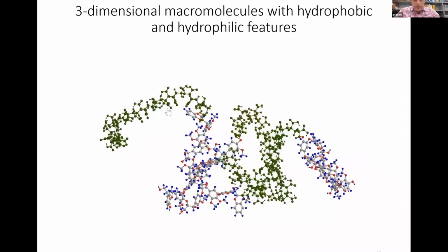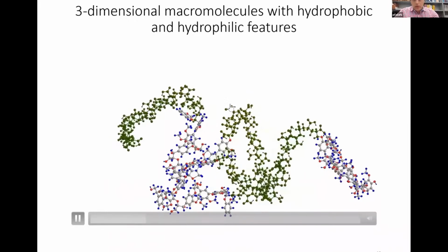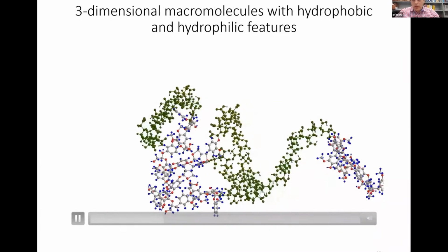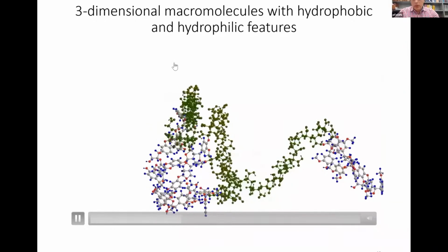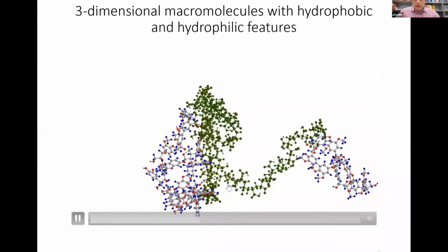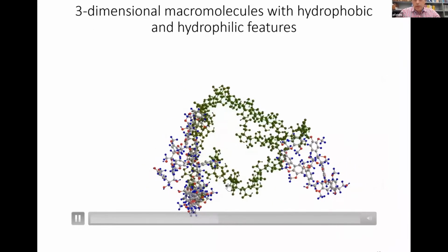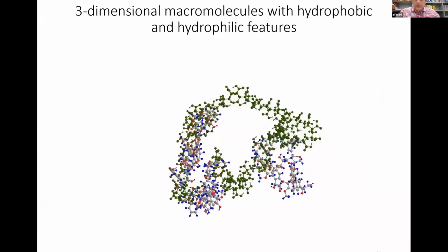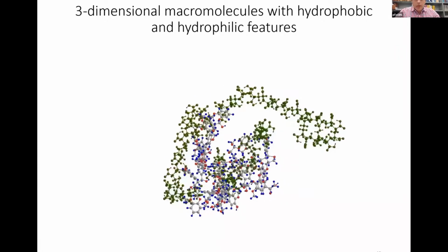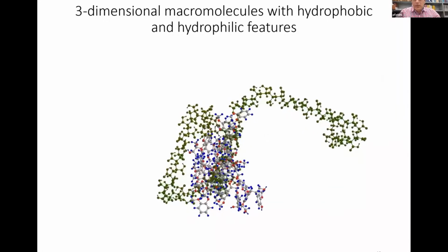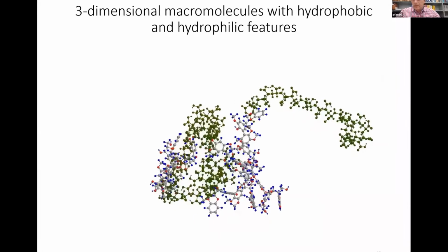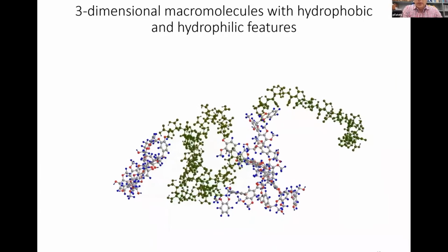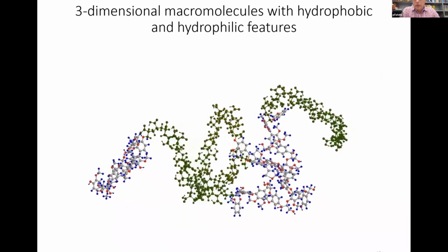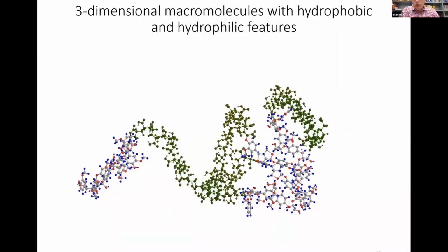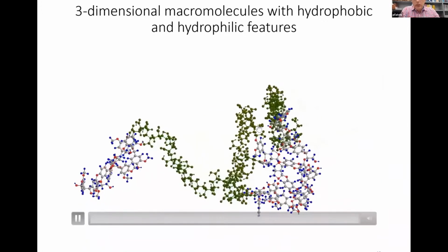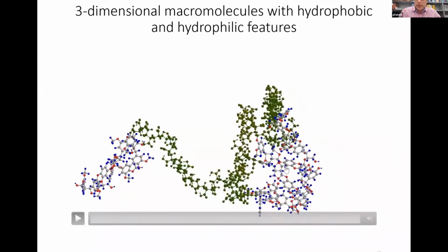So these parts are the lignin parts, the green parts are the monomer or the synthetic polymer part. And as you can see, we are talking about a three-dimensional large polymer that includes both lignin and the other synthetic part. What we have seen is that the efficiency of this lignin, as I showed you in the previous slide, is much better than the commercially used polymers. Why? Because we are talking about a 3D material rather than a linear one.